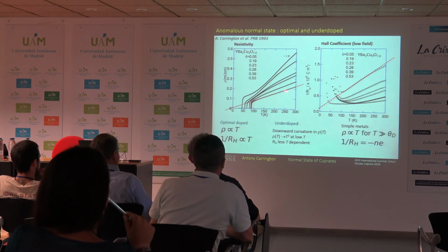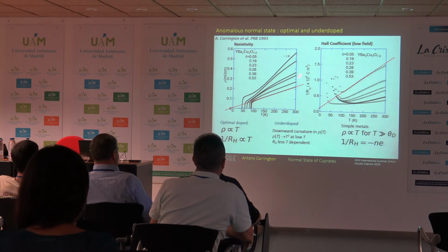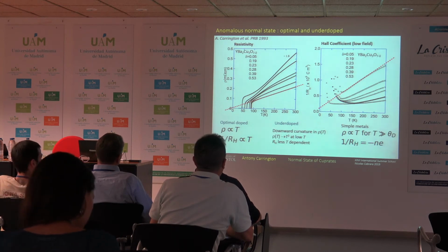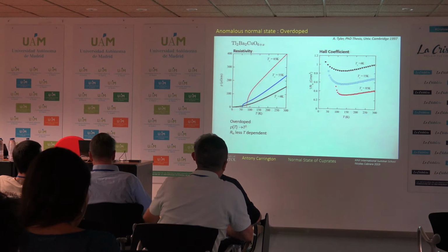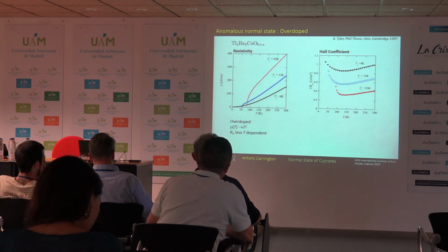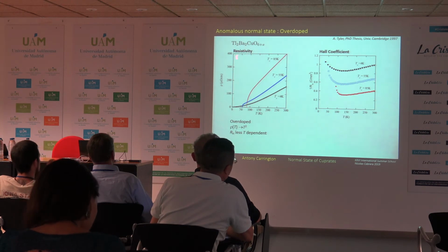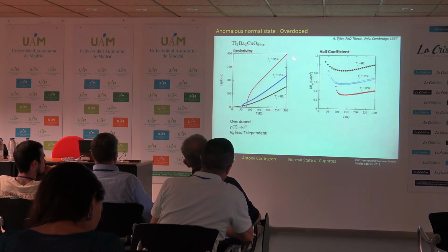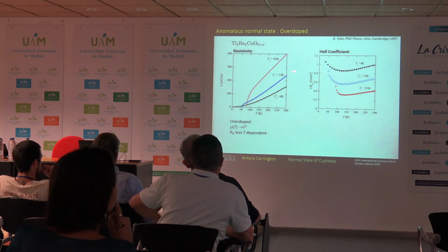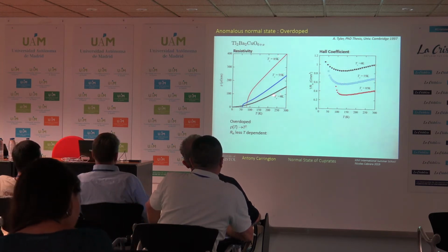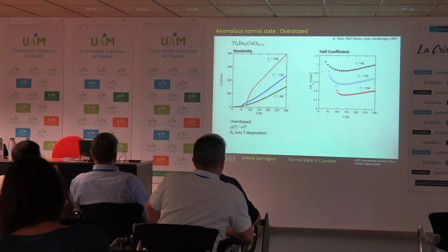So what we've looked at here is what happens at optimal doping and what happens when we underdope. What happens when we overdope? So what happens when we go to the other side of the phase diagram? The archetypal material to study this is not YBCO, but thallium-2201. And what's found is that the linear resistivity when TC is high gives way to something that varies much more like T squared when TC is very low.